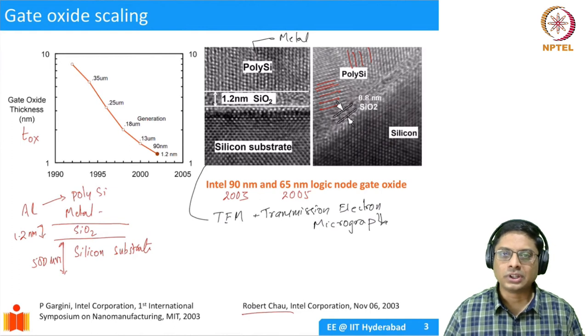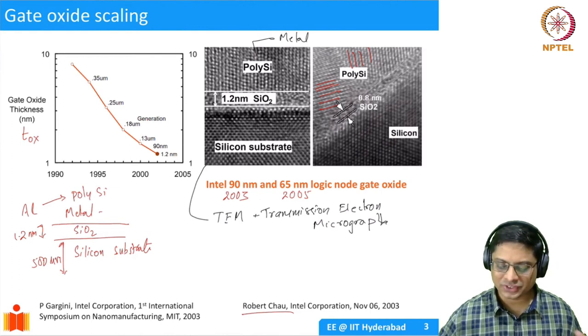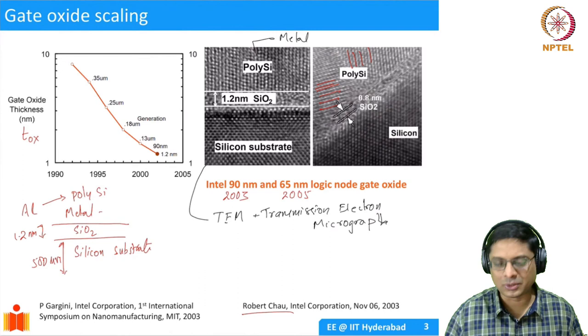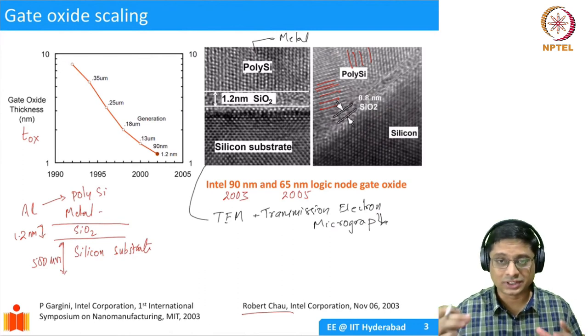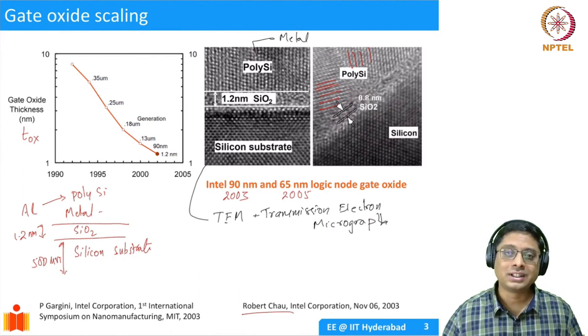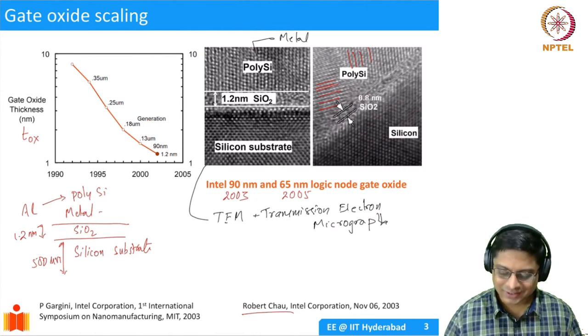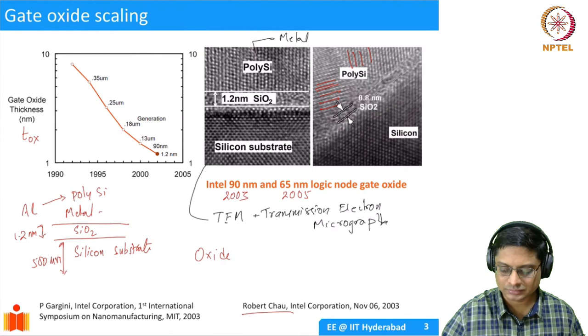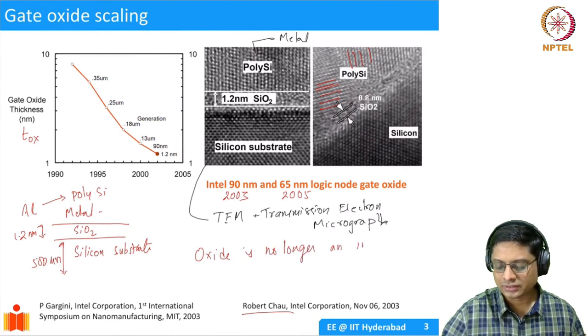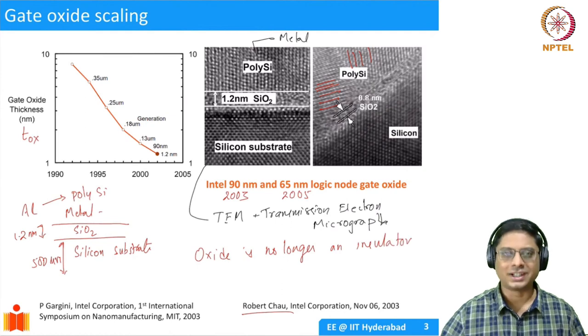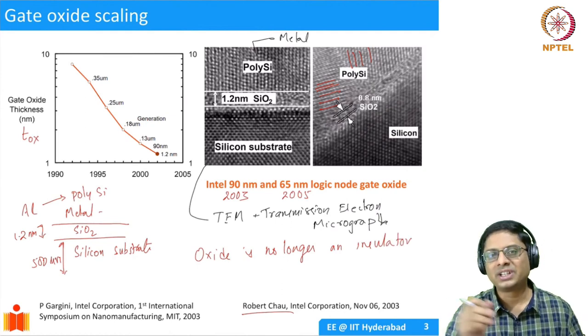So when the MOS capacitors became such small sizes, and the thickness of the oxide became very, very small, there were a lot of problems. One of the biggest problems was that oxide is no longer an insulator. It has a band gap, but the problem is it is very, very thin. So electrons were tunneling across the oxide.